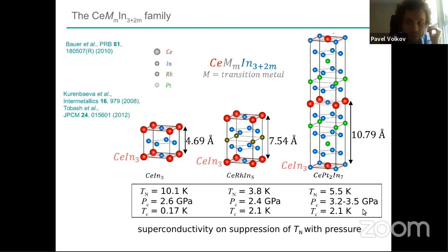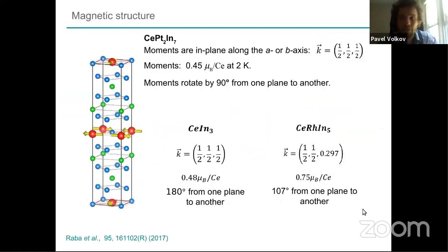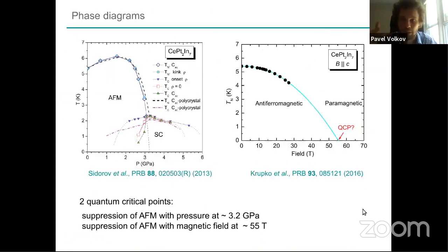Yes, my question is about the antiferromagnetic state. It seems to extend at least up to 35 Tesla. If you take the value of magnetic moment characteristic for cerium in this compound and calculate the corresponding energy scale, presumably 35 Tesla would correspond to something like tens of Kelvin, at least, while the Néel temperature is between 5 and 6 Kelvin. Isn't there a discrepancy here? The field is almost an order of magnitude higher than the Néel temperature. So wouldn't you expect the field to completely polarize and destroy antiferromagnetism? Why does it survive to such high fields?